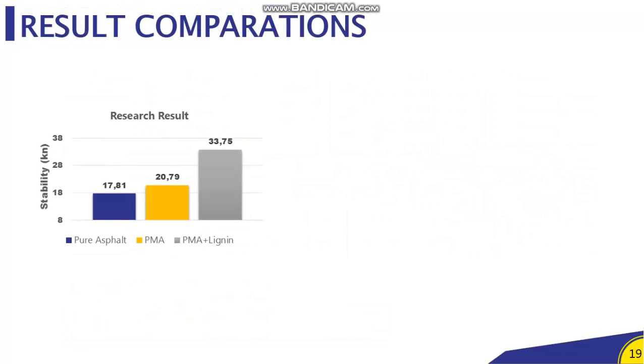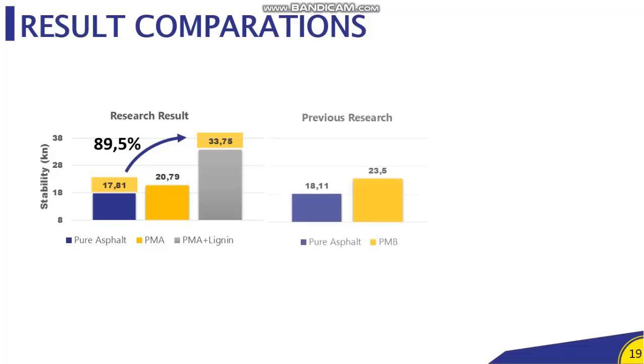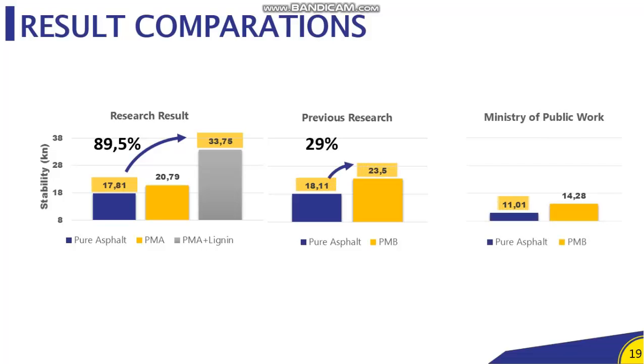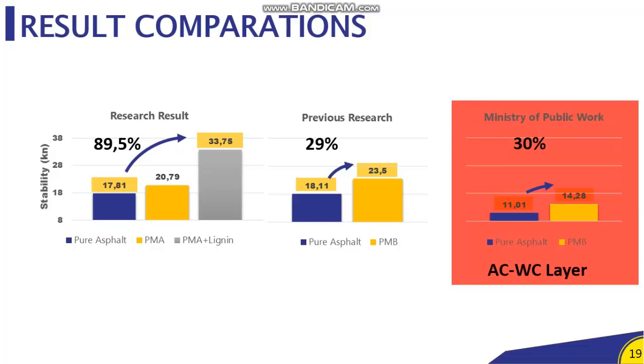And this is the result comparison from our research: we can improve the stability parameter up to 90% using the lignin coupling agent, whereas previous research could improve the stability parameter by only about 30%. And the Ministry of Public Works research result can improve the stability parameter by about 30%, but they applied it in the AC-WC layer.